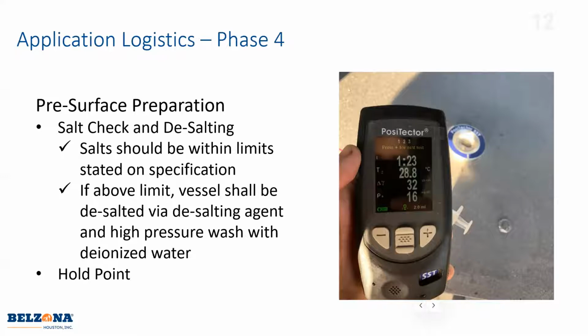And then one of the main things of the pre-surface preparation is, even though the vessel's been decontaminated, steamed out, cleaned out, sometimes you do have some salts within the metal. And one of the big things is you want to check that. So that's what this picture is here. It's checking, there's 16 milligrams per meter squared of chlorides. Our limit is 20, so we were good here. You want to make sure you're under the limit. That way you can blast and not have to worry about any flash rust, and also any blistering during the application. If you do apply it with high salts, there is a chance for blistering over time. So if we do find that it's high, we'll desalt it before we start blasting. And that's usually a hold point with the inspector.